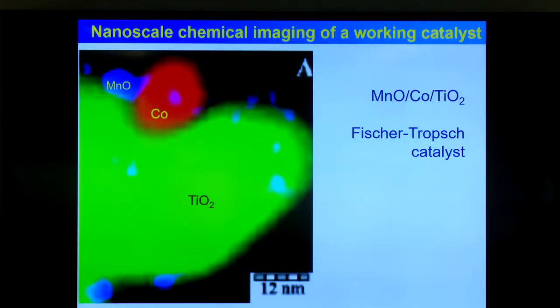This is the actual nanoparticle from the factory. This is a sample which directly comes from the factory in Qatar. And this is not X-rays, this is electrons. So we did electron microscopy, EELS, and then we colored it. This is the titanium L edge, the manganese L edge, and the cobalt L edge. This is 10 nanometers, so you can see a 10 nanometer sized cobalt nanoparticle, with manganese attached to it.